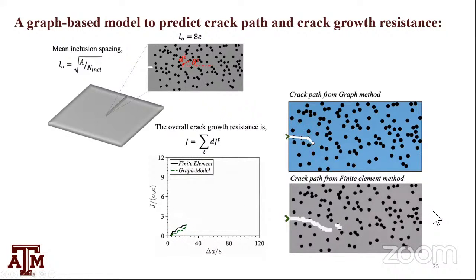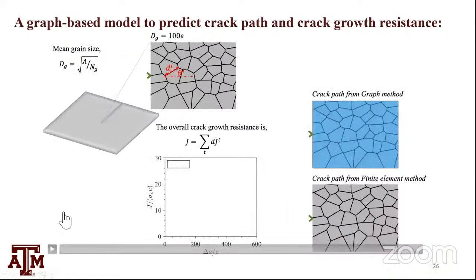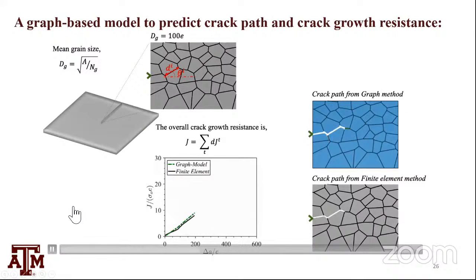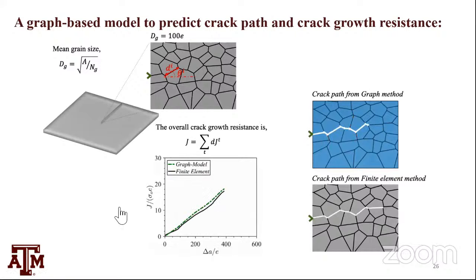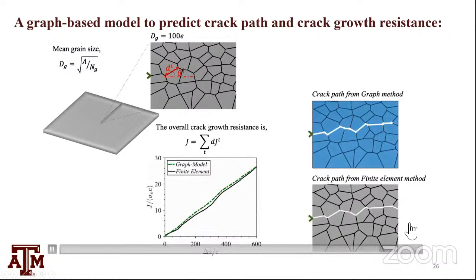Now, how does it work in grain boundaries? This was the easier problem, so it works even nicer. Every time I have to only pick either this or that, right? So it's pretty easy to pick, and we can keep doing. We get very reasonably close grain boundary fracture paths, and very reasonably close J-delta-A curves.